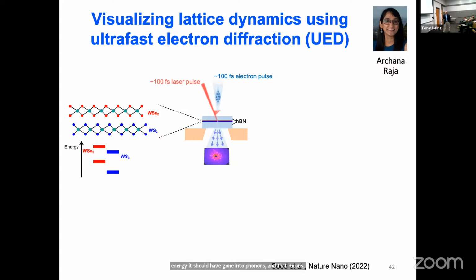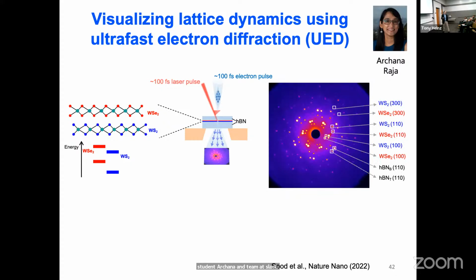And collaborating with a former student, Archana, and team at SLAC, we actually have a very nice way of looking at this thing with electron diffraction. So electron diffraction shows the crystal structure. You get this very pretty thing here after appropriate colorization. But you can actually see the lattice of each of these two layers in the heterostructure, two semiconductor layers, and then you get some spots from these supporting layers here as well.